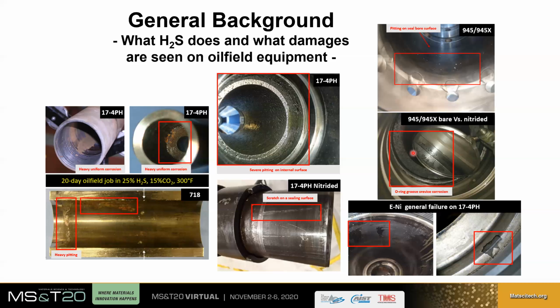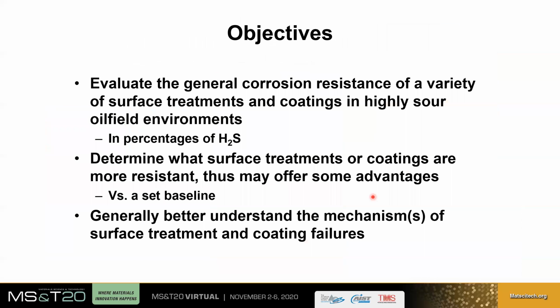If you look a little bit toward the right here, we see more pitting, including within an O-ring groove. We see some flaking or spalling of a hard coating here, an electroless nickel plating. So we can see that the surface treatment and the plating in use today have deficiencies, and this is what we want to look at specifically in this short investigation. So the objectives are pretty clear. Number one, evaluate general corrosion resistance of surface treatments and coatings in a highly sour environment.